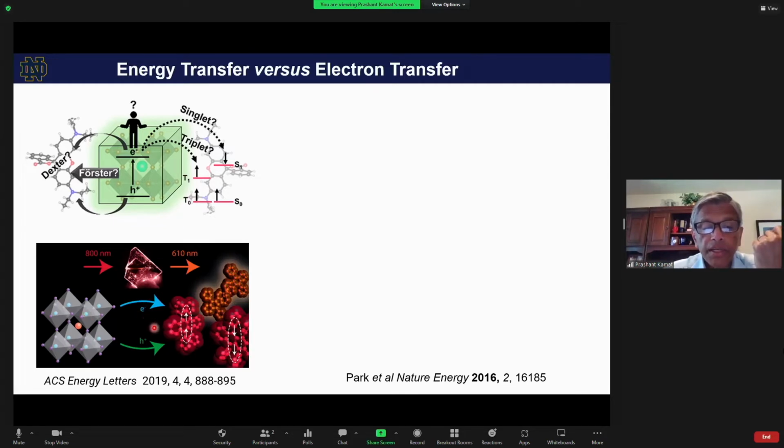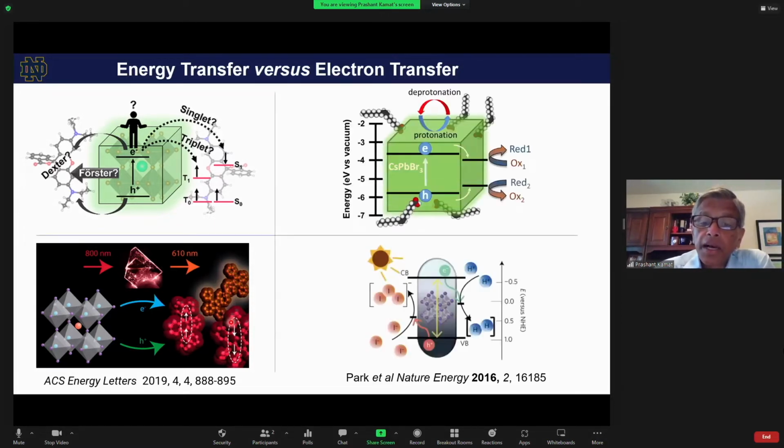Here is one of the studies on upconversion. They add rubrene and DBP, which is a perylene dye, and then excite with 800 nanometers and generate 600 nanometer light. So what is the mechanism that underlies this? They do claim that you transfer electrons and holes to create this excited state, which is essentially a Dexter mechanism. Then two triplets give you an excited singlet, and then they transfer energy to this DBP to give you this upconversion. But the underlying mechanism has not been settled; although there are papers, I will show you one paper where it is wrong, but one needs to get a clearer picture.